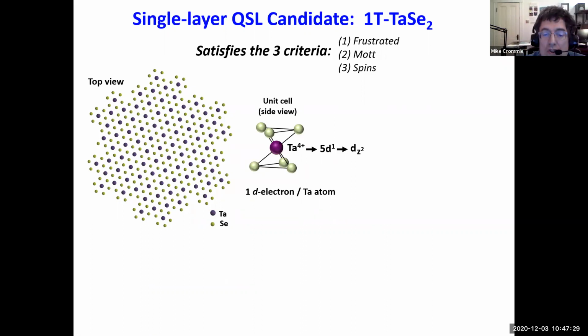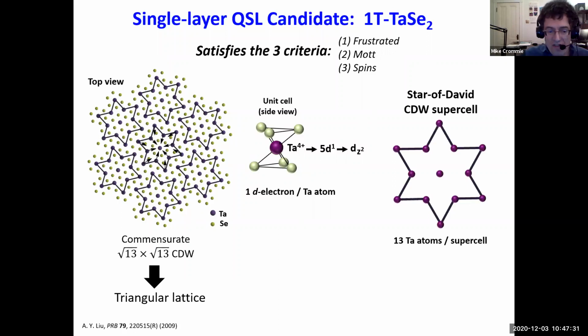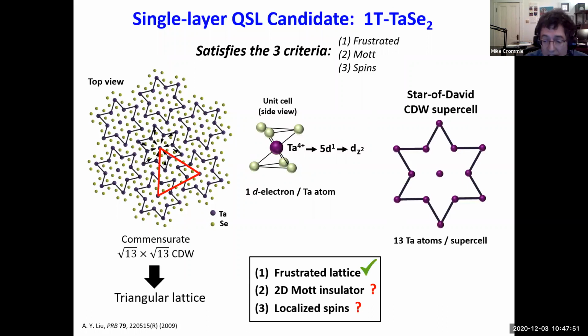But there's one other nuance to this, which is the fact that electron-phonon coupling in this material causes it to form a charge density wave. It's a really funky charge density wave called a Star of David CDW, where the CDW supercell is this Star of David. This is due to electron-phonon coupling, and you can actually calculate this with density functional theory. The lattice that we care about is this triangular lattice of the CDW. So that's the important lattice for this problem.